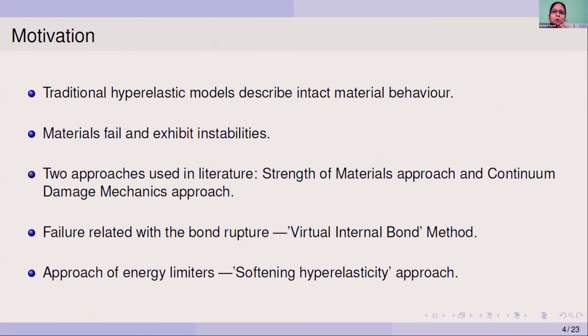So let's now turn to the modeling of this damage onset in these quasi-brittle materials by addressing their constitutive behavior of nonlinear brittle elasticity. As we know, a hyperelastic constitutive model is developed to describe the nonlinear elastic response and derives the stress-strain relation for the elastic material from a strain energy density function. Traditional hyperelastic models are aimed at describing the intact material behavior and allow for unlimited increase in strain energy. However, we know that no real material can accumulate unlimited strain energy, and materials start to exhibit instabilities after reaching a certain critical value of strain energy, and they fail eventually.